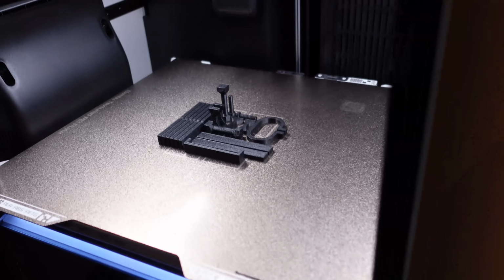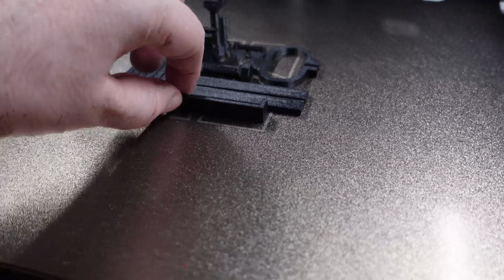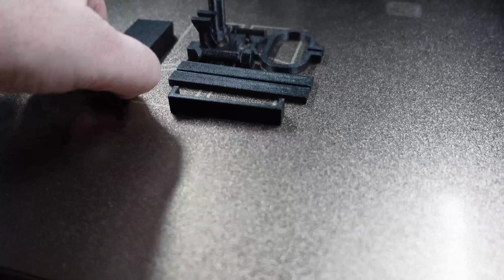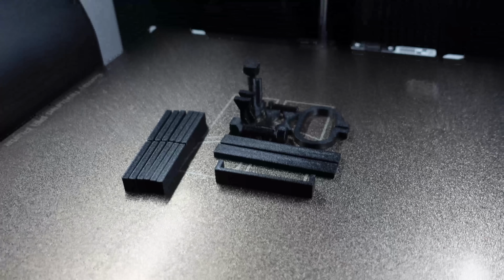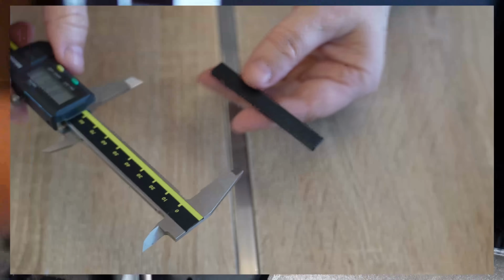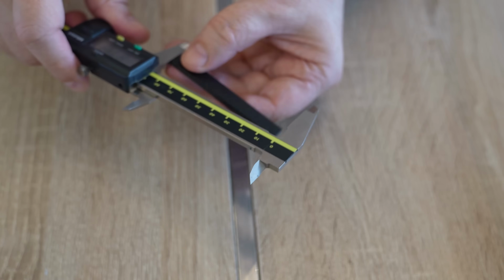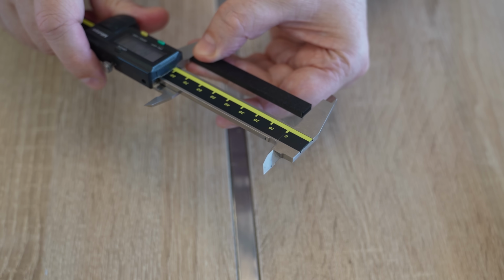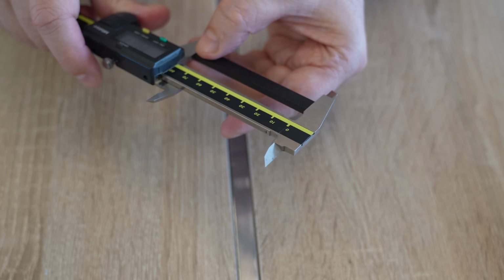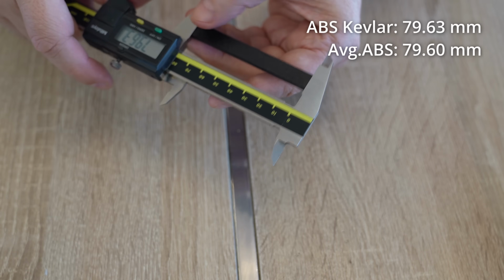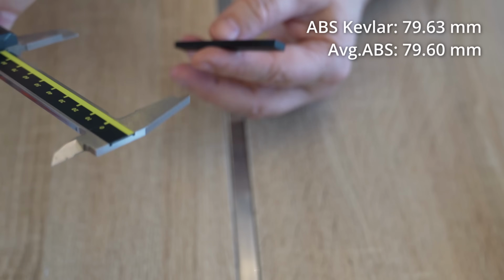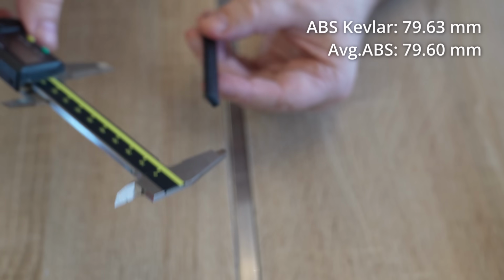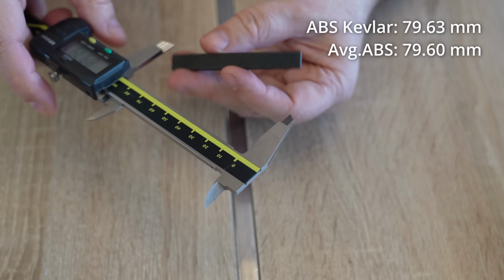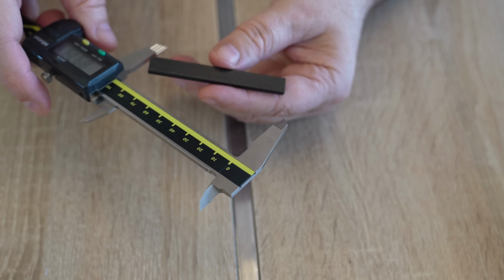I wasn't here when it was finished. It was printed half an hour ago. But even now the adhesion is quite good, but already removable. Let's check the shrinking. The design length is 80 mm. Now I will try to measure above the elephant foot. 79.63. This means the shrinking is not much smaller compared to the regular no-fiber reinforced ABS, which on average will be 79.6 mm.